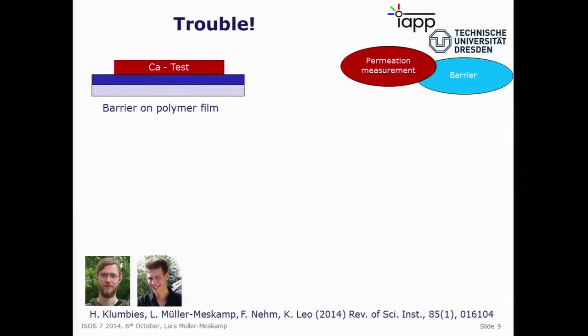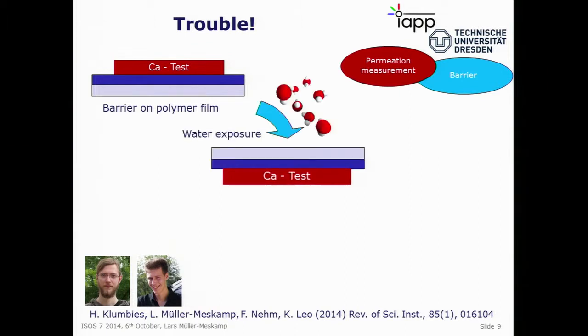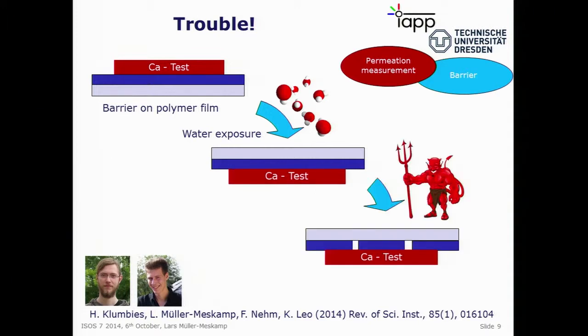This is all very nice, but it gives us a lot of trouble because this is what we usually do. We have the barrier on a polymer film, so you have a PET or PEN, and you have a very thin barrier layer, and put the calcium test on top. And what the calcium does on water exposure is it expands. This is in general not a big deal, because we have only 60 nanometers, it's not so much. But if you put the calcium test directly on the barrier, it will break the barrier, so you cannot measure anything. It kills the barrier.